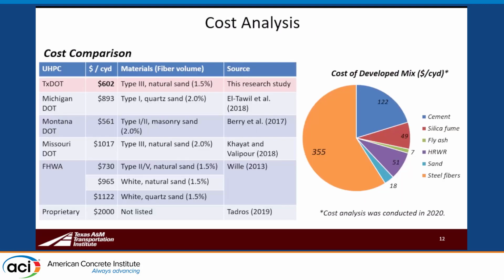So this is a cost analysis, just to wrap up the material side of the UHPC study. When we did a cost analysis back in 2020, we were coming up with about $600 per cubic yard. This compares well with some of the other studies that range from about $560 to a little over $1,100 per cubic yard. Proprietary mixes could be on the order of $2,000 per cubic yard, which may be okay as we're looking at smaller volumes, but we might be interested in trying to bring that cost down for something like a girder where we have a fairly large volume. And that was what TxDOT was interested in.